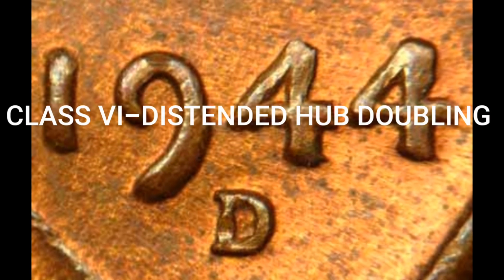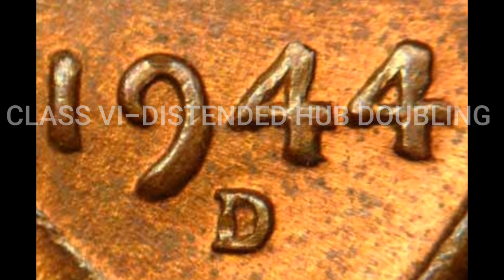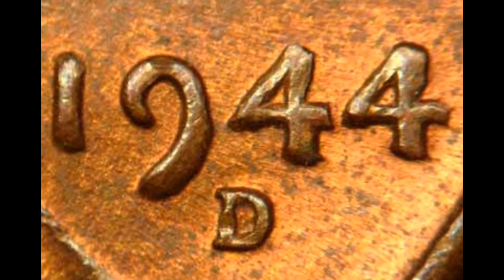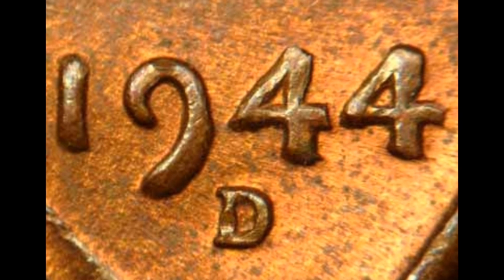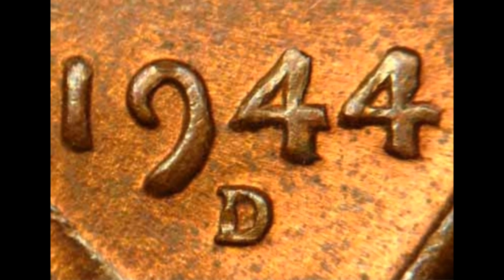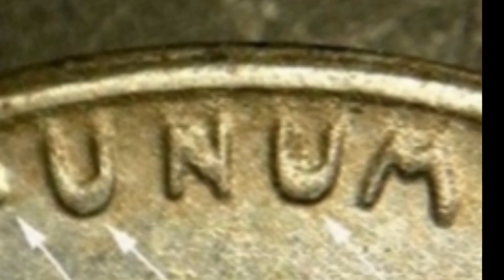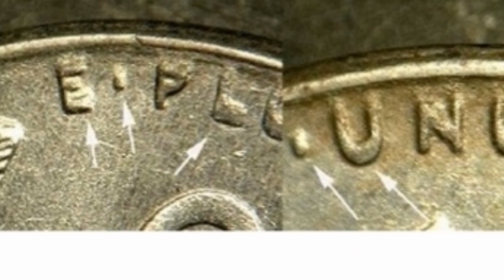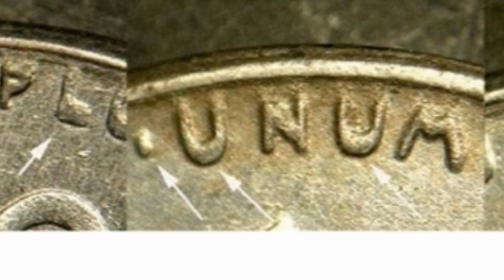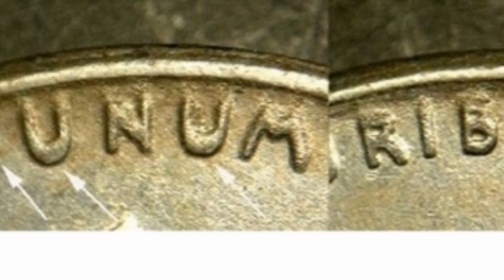Class 6, Distended Hub Doubling. This class is generally caused by using hubs to impress designs into improperly annealed dies. The design flattens out and becomes stretched or distended toward the outside of the design. A lot like Class 2 doubling, the Class 6 double dies generally show characteristics close to the rim. This class usually shows up as extra thickness.